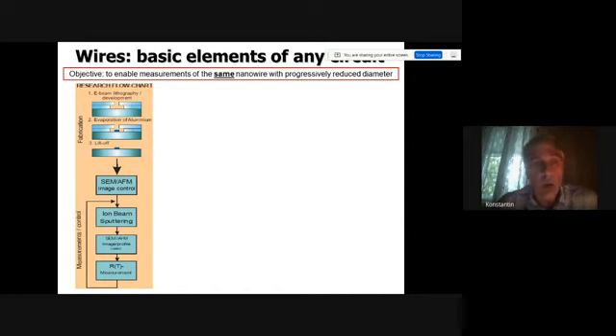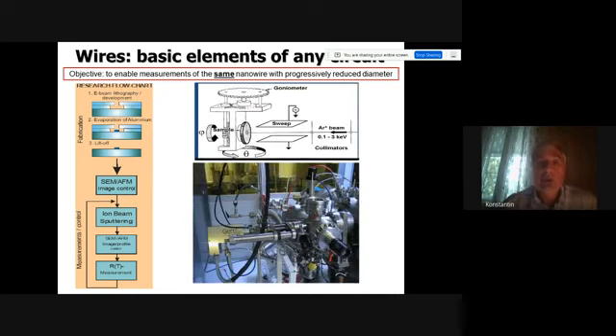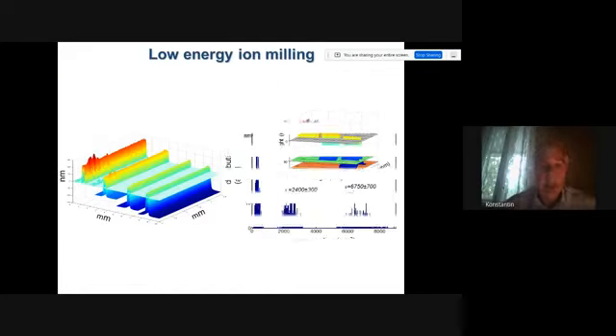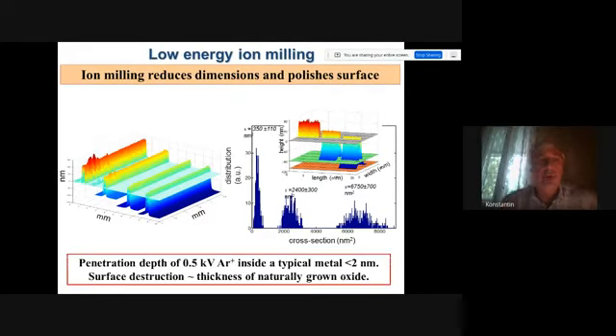So we used our E-beam technology, which is conventional, then studied the sample, let's say measured resistance versus temperature, observed it also with an electron microscope to check that there are no obvious artifacts, and then subjected it to ion milling produced by a low energy ion gun. So the energy is typically a fraction of a kilo-electron volt, and we also sweep the structure under the ion beam. Do you hear me well? Yes. Great. So what is obtained is shown here.